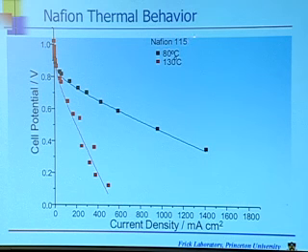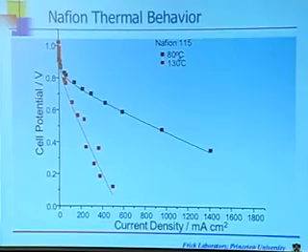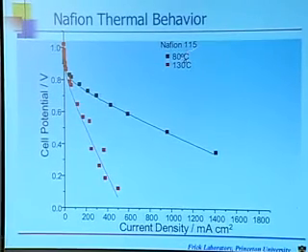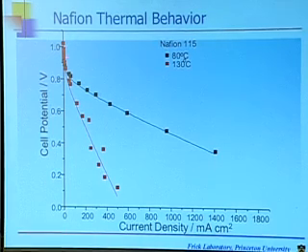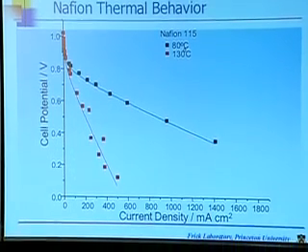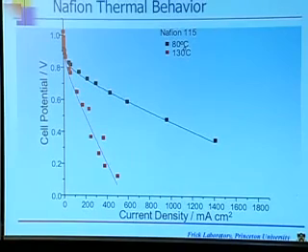It turns out the way they've ratioed this, a smaller number is better. That is, it has more acid in it. And it's done in grams. It's not done in moles. And so it doesn't have any immediate significance other than this is a fairly high acid loading in this polymer, 115. So you take that polymer, you slap your electrodes on, very carefully, and you run one of these current voltage curves, and you get the black curve that I am showing you right there. Okay, and that is not a bad curve.